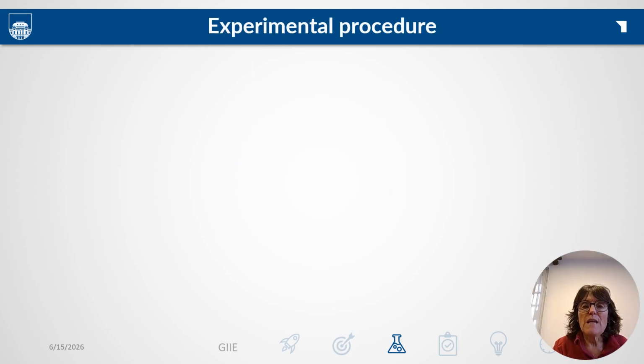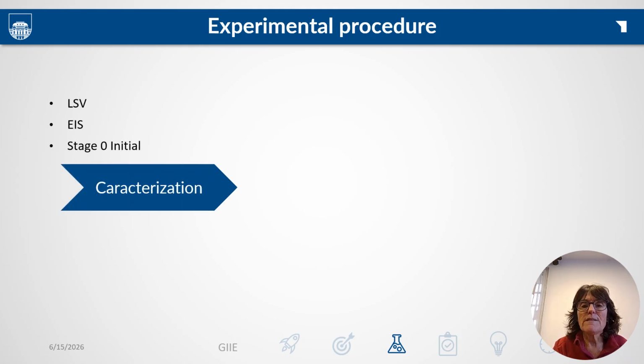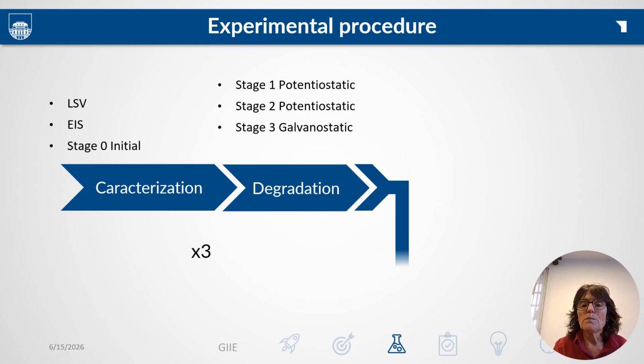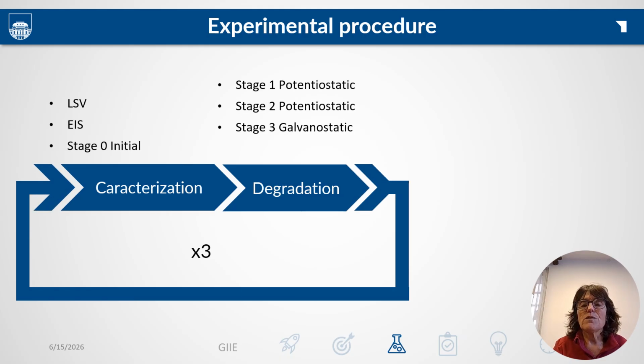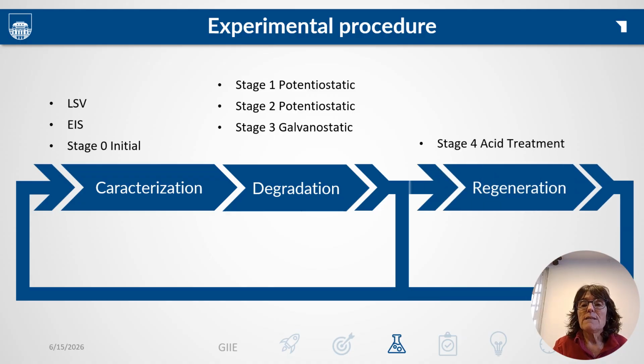The protocol was the same for both assemblies and is summarized here. It consists of 6 stages. Stage 0 is the initial baseline characterization. Stages 1 and 2 are potentiostatic degradation steps at 2 volts for a week. Stage 3 is a galvanostatic degradation step at a current density of 90 milliamperes per square centimeter, also for a week. Stage 4 is the regeneration procedure, which implies the immersion of the assembly in 1 molar sulfuric acid at 80 degrees for 1 hour, followed by rinsing with ultrapure water.